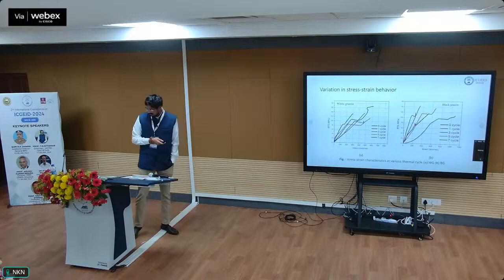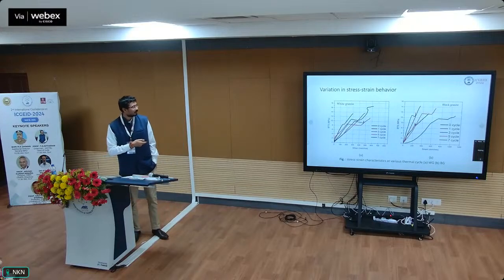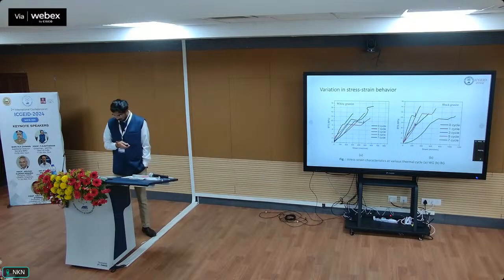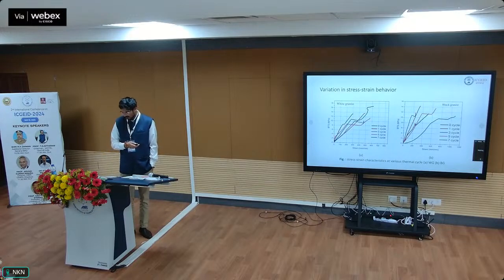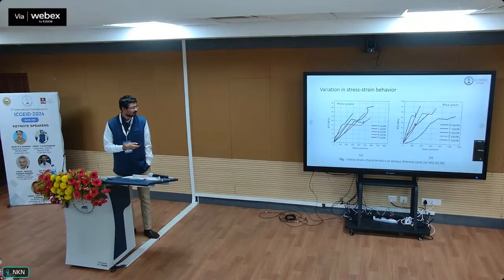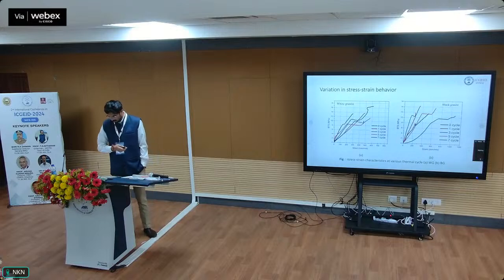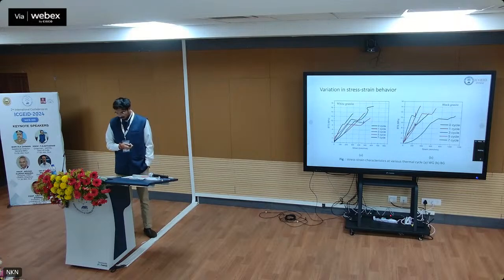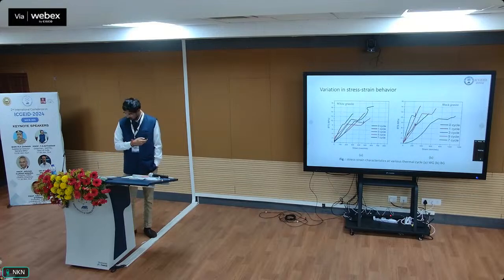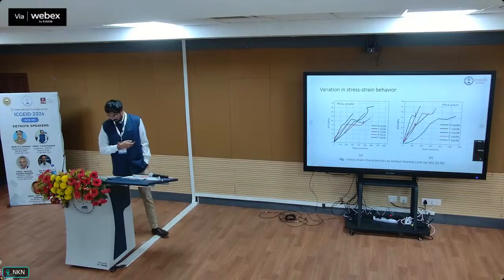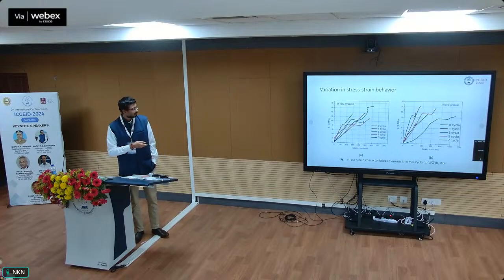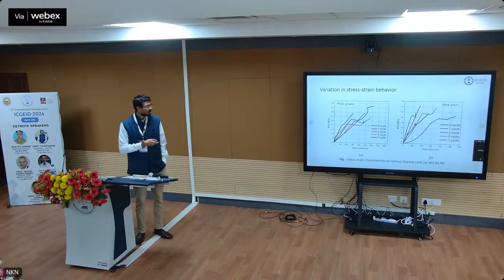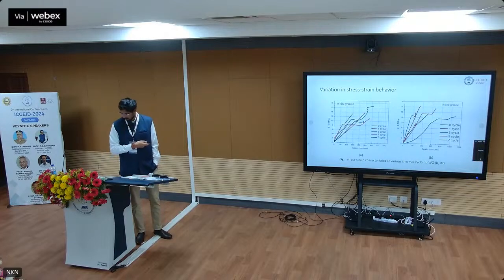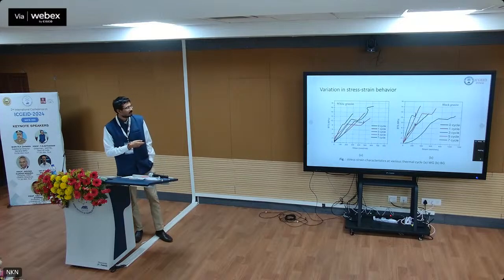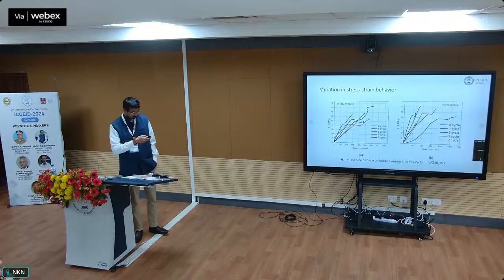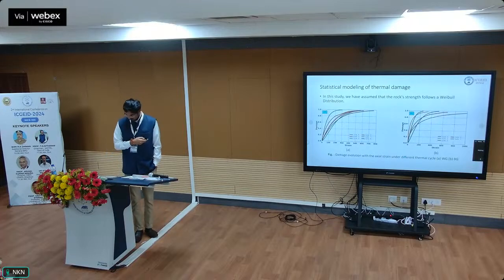So we have done the Brazilian tensile test on these rocks, and we have observed that the white granite, due to its more stable mineralogical composition, is showing a strain softening effect, and the black granite is initially showing strain hardening, then it is showing strain softening. It can be explained because the black granite has more thermal expansion anisotropy than white granite, and it has more mineral heterogeneity.